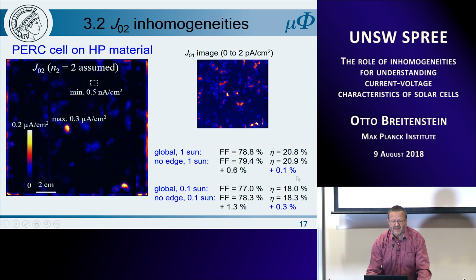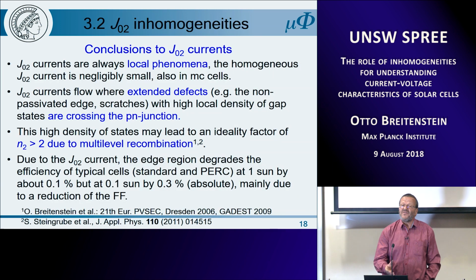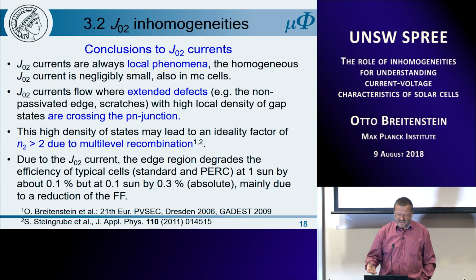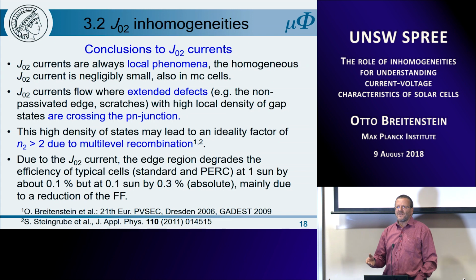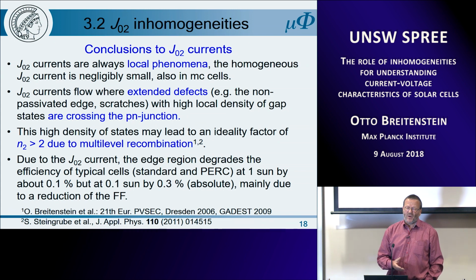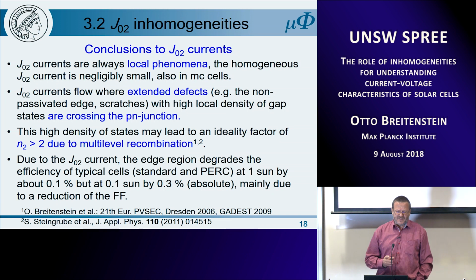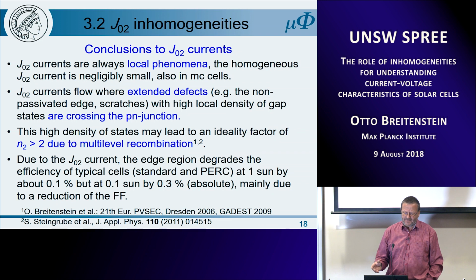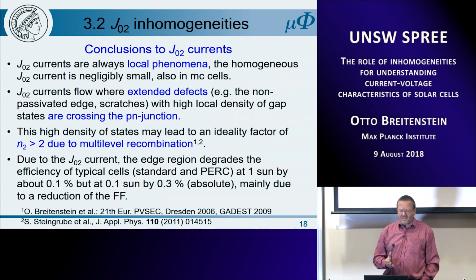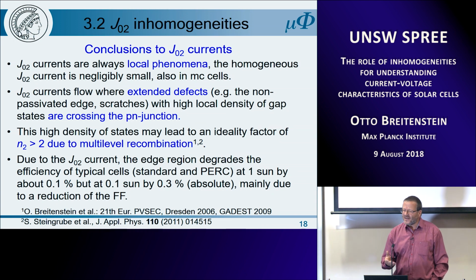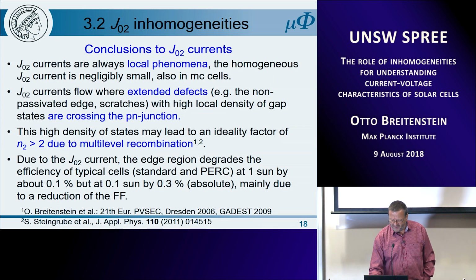Which brings me to the conclusion that J02 currents are always local phenomena, because they are connected with these extended defects, but macroscopically they are small. And so the homogeneous J02 current, which according to the textbooks is also existing, is negligibly small in all these solar cells. It's so small that it cannot be detected by lock-in thermography. So this J02 current flows where extended defects with a high local density of gap states are crossing the pn-junction, and this high density may lead to ideality factors larger than 2 due to multi-level recombination. I already have shown the numbers. So this J02 current degrades mostly the fill factor, and mostly at small illumination intensities.